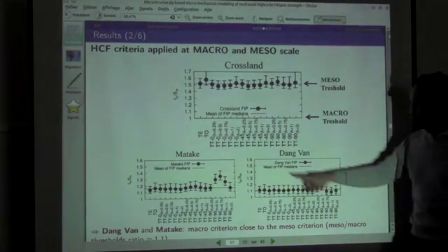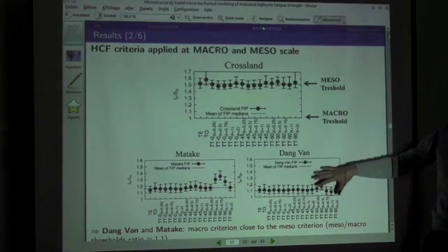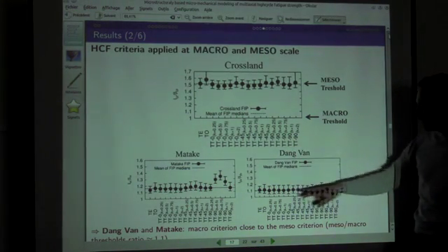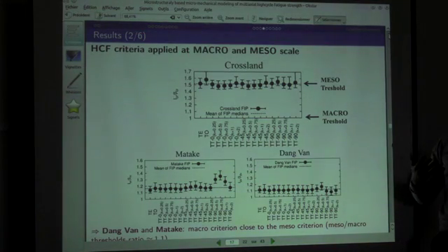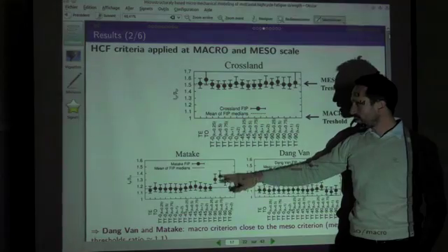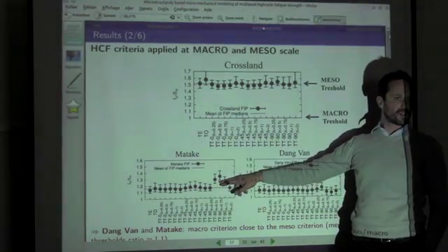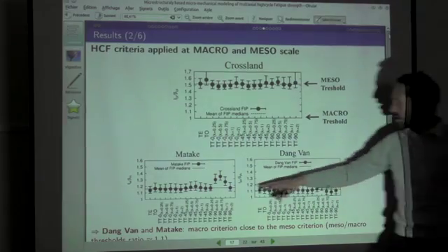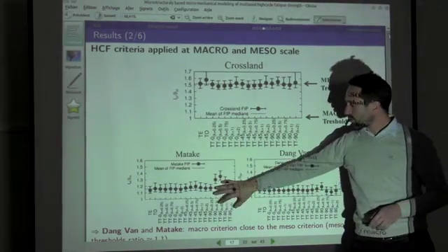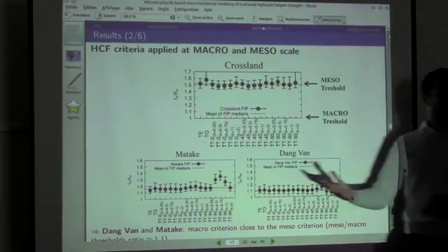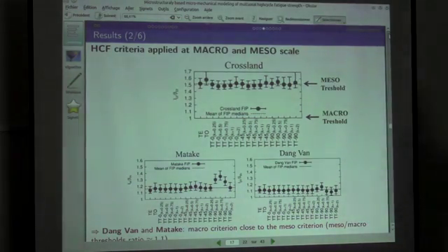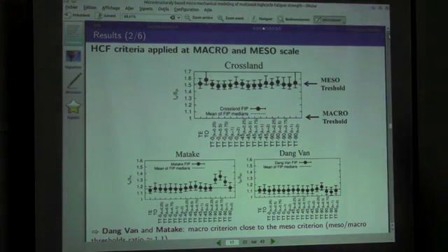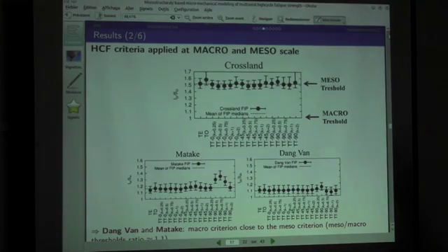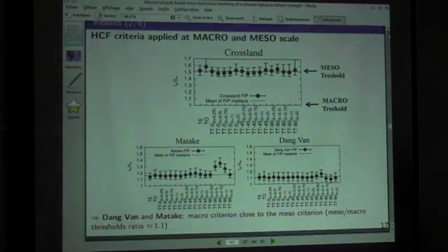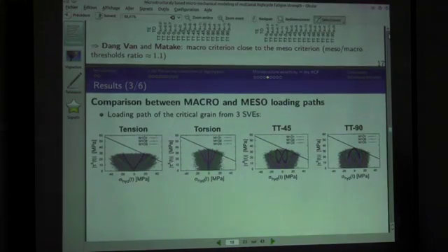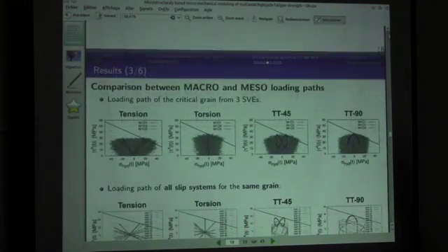A point that is interesting is that depending on the criteria that you are using, you don't have similar response between the mesoscale and the macro scale. For example, for such criteria here, you see that for some loading cases you have an offset of the response, it's not linear. So it means that locally, using a microstructural analysis, you have a different response or different sensitivity to the loading than the macro response. So using this type of analysis, you can try to evaluate, depending on the criteria you are using, different sensitivities to the macroscopic response.